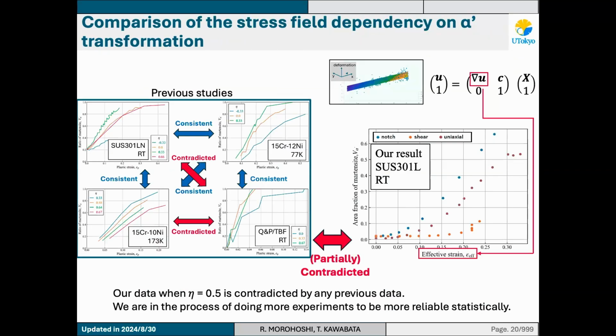By doing a lot of stuff, as I said, finally we could identify the effective strain by calculating the deformation, because we represent the deformation as a single linear function, so we could represent a single effective strain. So finally, we could compare the previous studies with our own. However, our data when the stress triaxiality is about 0.5 contradicts any previous data. So we are in the process of doing many more experiments to validate which is correct, mine or others.